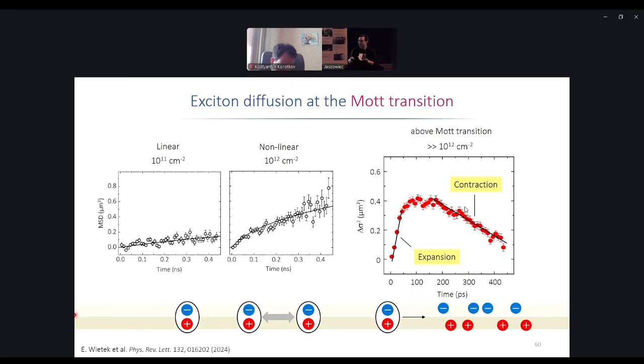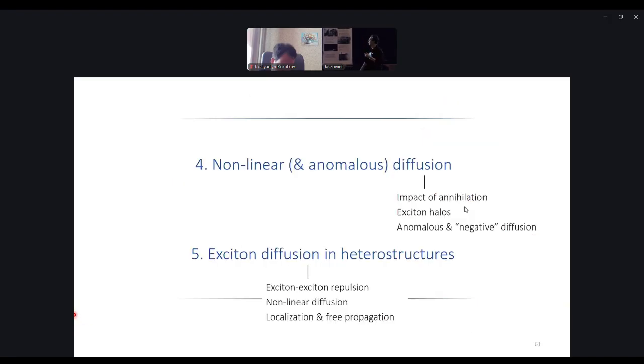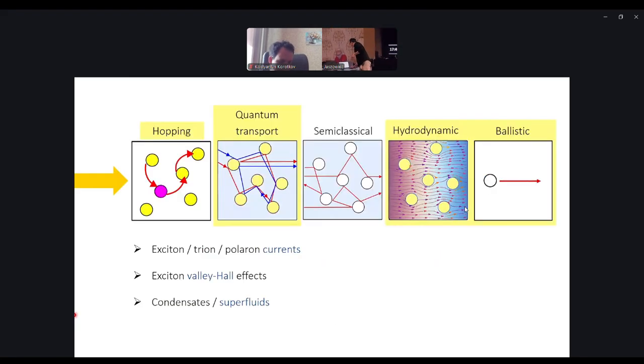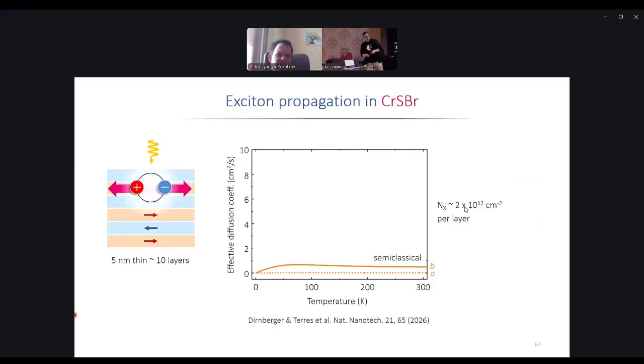It just means that you get highly nonlinear behavior under conditions where you start expecting different contributions from excitons and from plasma. And with this, we would finish on the impact on annihilation, exciton halos, negative diffusion. For heterostructures, I showed you the relevance of exciton-exciton repulsion, nonlinear diffusion, localization, and free propagation. One last example, just because you have a bit of time, just one example.